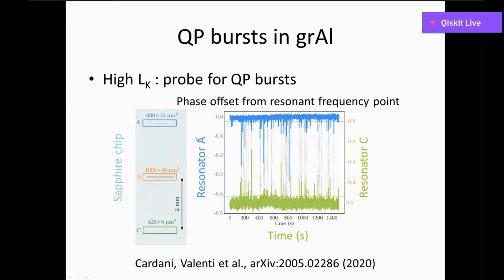What I show here are the phase response of the resonant frequency point, or better yet, the offset from this point, for resonator A and resonator C over time. And we do observe the drops that I mentioned. And when these two drops appear at the same time in the two resonators, the drops are connected with dotted lines. Note that, for clarity, the y-axis referring to resonator C is inverted.